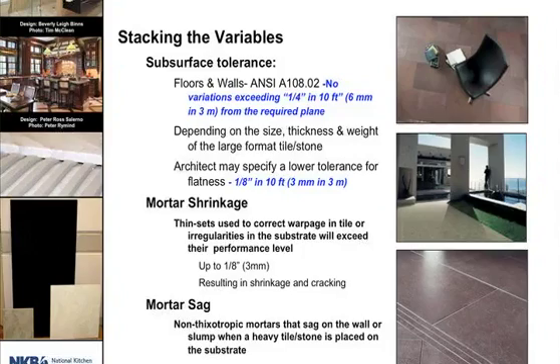We also have to look at mortar shrinkage. If you're using large format tile and the subcontractor says 'no problem, I'll fill that with thinset,' throw him off the job. Thinset is not meant to build up a floor — it's meant as a thin bonding coat to bond tile to the substrate. Thinset, like any concrete material, will have some shrinkage. The more they build it up, the more it's going to shrink. You may not see problems at first, but a couple of months later when someone rolls in a new refrigerator and creates point loading — snap. The thinset has shrunk and pulled away. Never use thinset as a leveling bed. There are proper patching compounds for that.